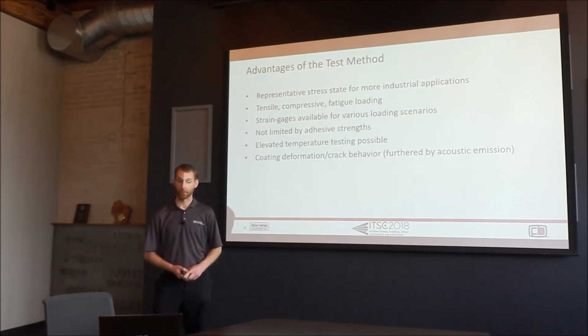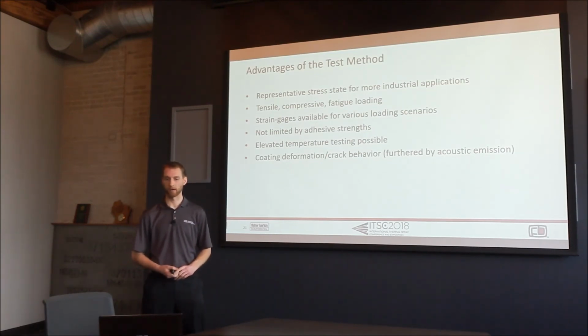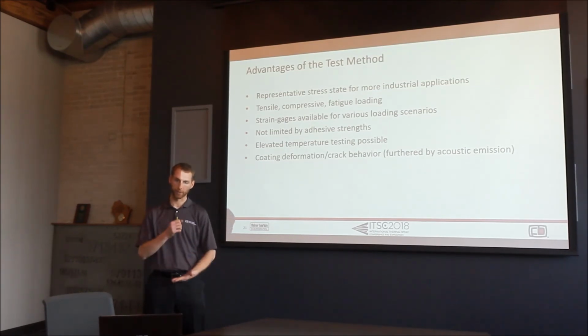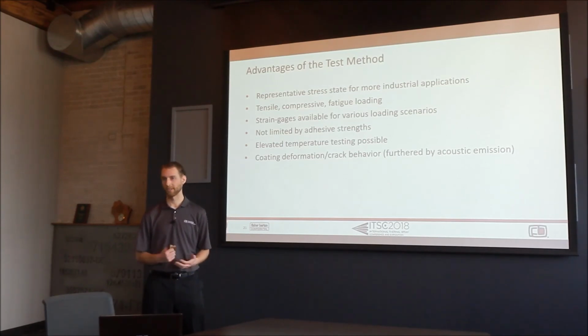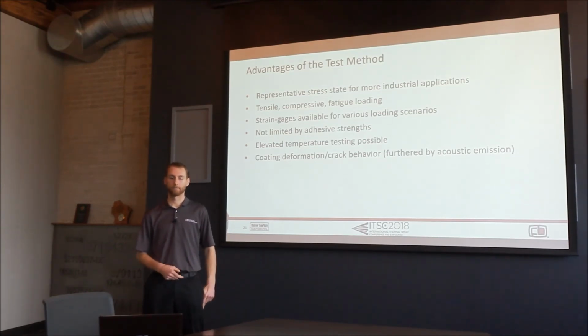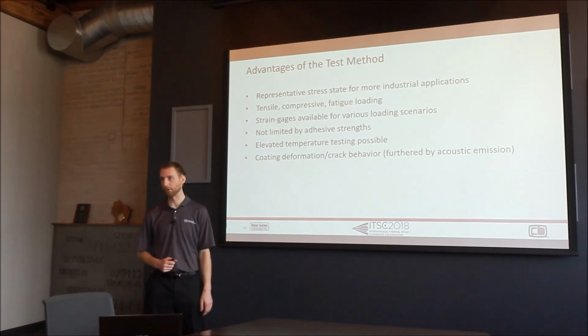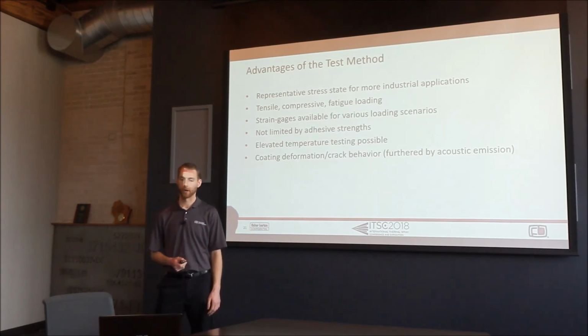Really the main advantage that we see with the 4-point bend method is that it is more representative for industrial applications from our perspective, as opposed to C633, which is pulling normally to the surface. That's just not very common from what we see. This test opens it up for multiple loading conditions under tensile, compressive, or fatigue loading. With those different loading conditions, you can have different strain gauges to look at the stress in different orientations. We're not limited by the adhesive strength as you are with C633, from the strength standpoint and also temperature. Different strain gauges could be used for higher temperature testing if that's your application.